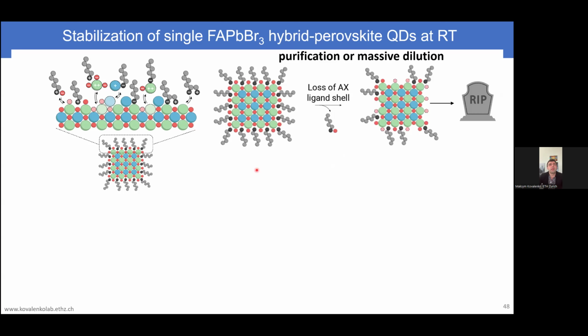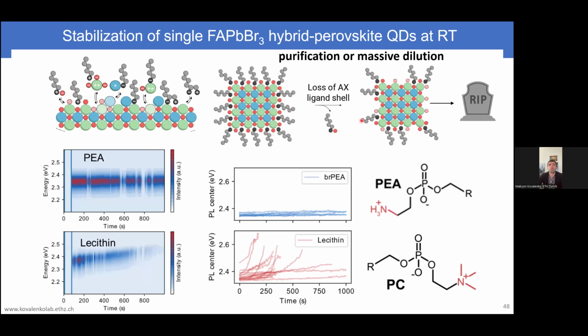And here I would like to emphasize that when we prepare these samples for single dot spectroscopy, you remember initially we discussed you need to disperse them microns apart of each other. So you have to actually dilute your colloid by tens to 100,000 times. You get very homeopathic sort of concentrations, and by doing so, you basically multiply the ratio between the residual moisture and residual oxygen, which is unavoidable in a solvent, no matter how dry is that. So you multiply these residual enemies with respect to your quantum dot, and plus the ligand desorption, even these best ligands, will cause damage to the surface and potentially the loss of the ligand.